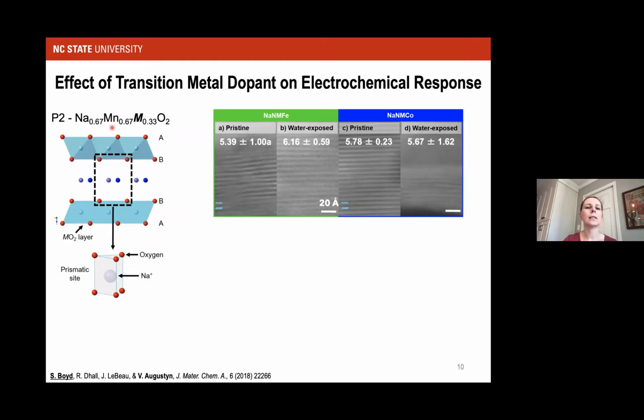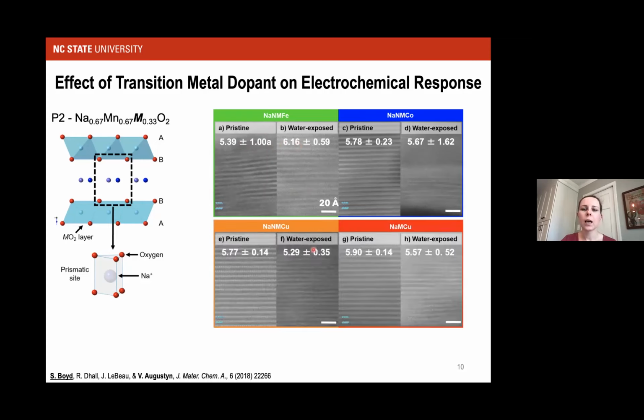It turns out that depending on what the dopant is, what the other transition metals are around manganese, to a large degree determines how stable the material will be when exposed to ambient air that contains humidity or an aqueous electrolyte. We noticed that if we had, for example, iron in the structure, the material was very readily becoming hydrated upon exposure to water. So you can see that in the increase in the interlayer spacing. On the other hand, if the layers contained copper, then their ambient stability was much improved, and before and after water exposure, we could still image these beautiful layers of the transition metals.